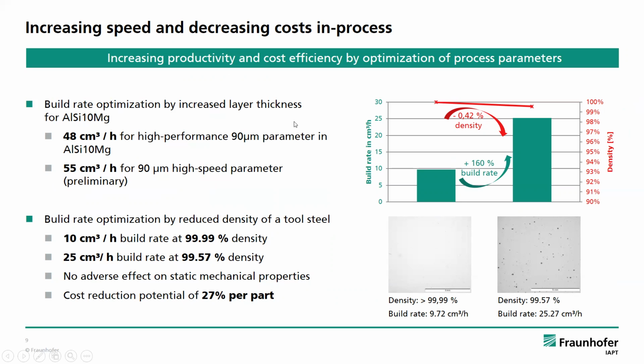One means to reduce build-up time is, of course, increasing the layer thickness during the recoating. And in collaboration with an industrial partner, we have developed 90 micron parameters for AlSi10Mg for high performance, which means in this case maintaining high density and ductility in the part. We're in the range of 48 cubic centimeter per hour for AlSi10Mg here. And for the high speed parameter, based on a one laser solution, we're at 55 cubic centimeter per hour. Some investigations are still ongoing to increase this.